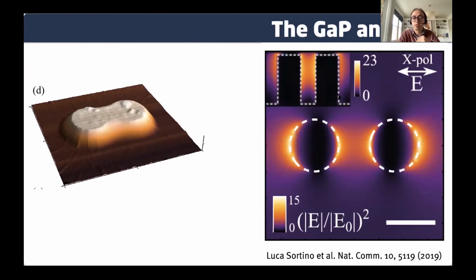Now, the antennas interact with the light very strongly, and they confine the light. And you see here on the plot on the right that the field is much higher inside the antennas, on the order of 23 times more inside. This would be the ideal place where you would put your emitter, in between the two discs. This is very hard to do, but the good side is that the field leaks outside a little bit. And so when we place the material on the very top of these antennas, we are still coupling quite well to the antennas. And you see that there's a field enhancement just on top of the antenna.